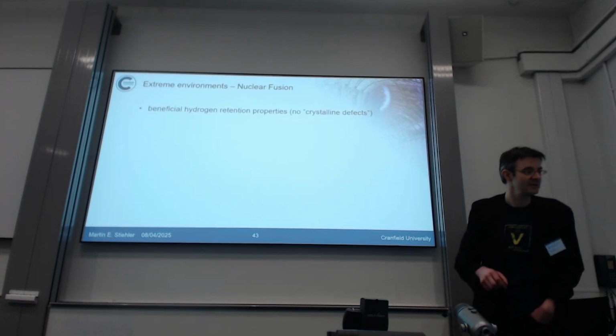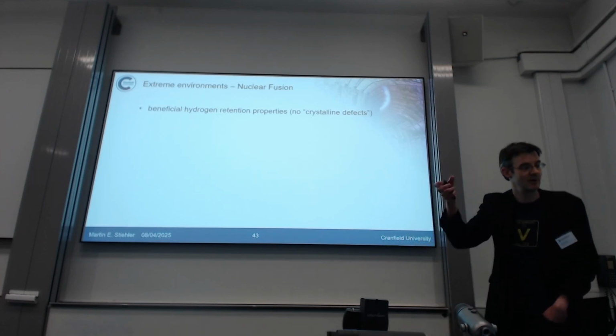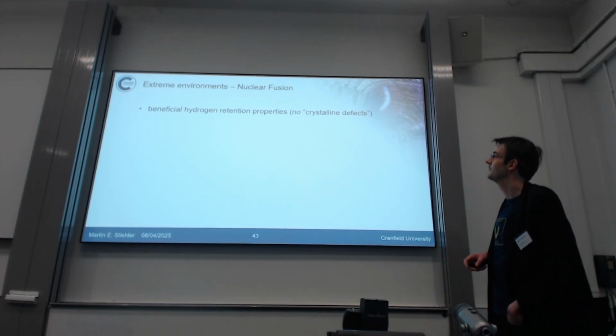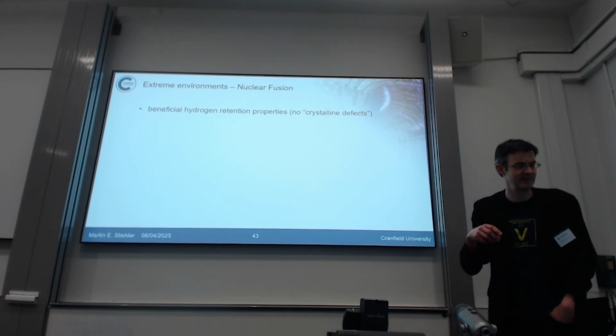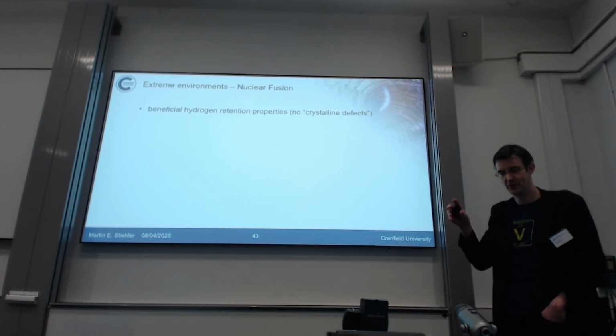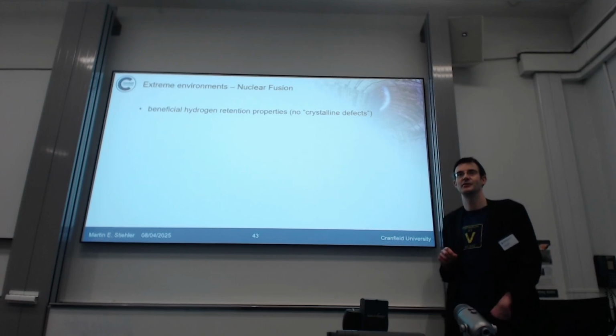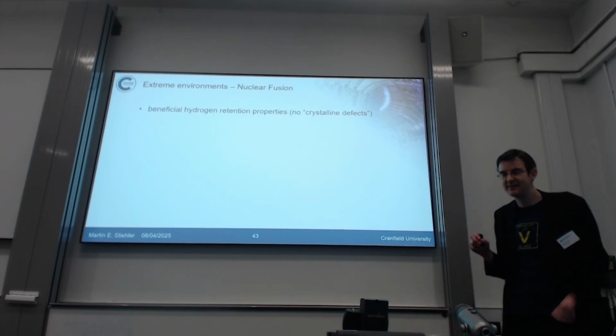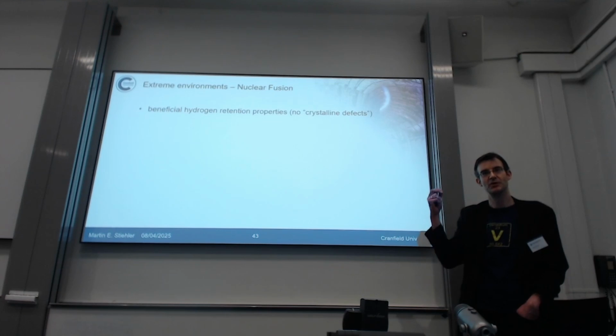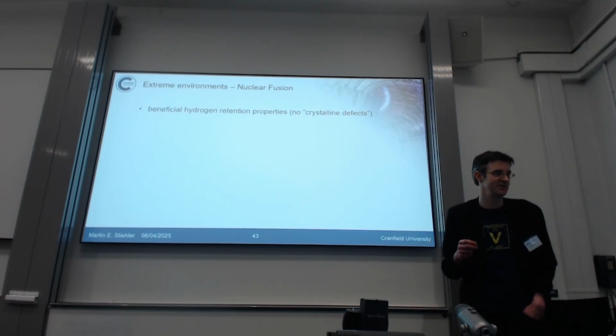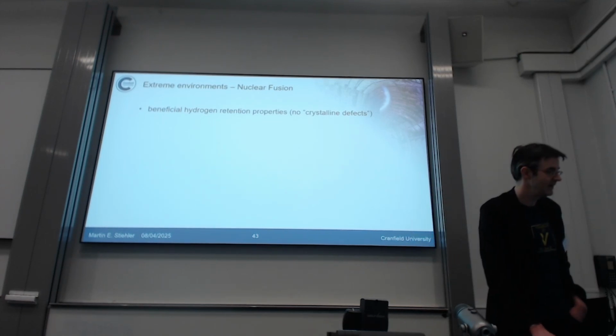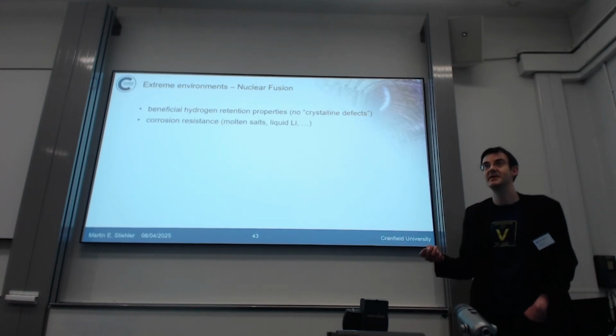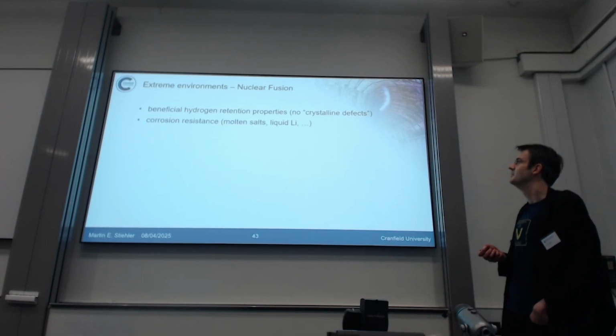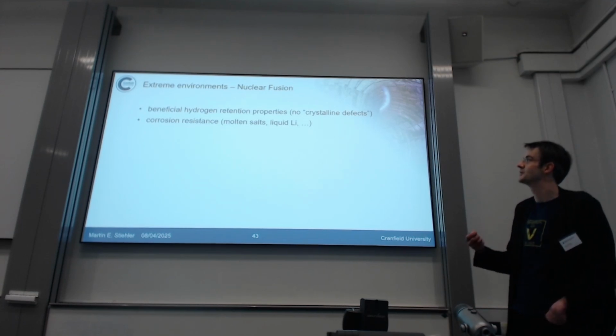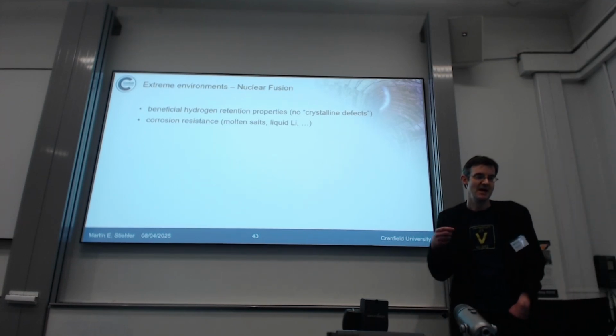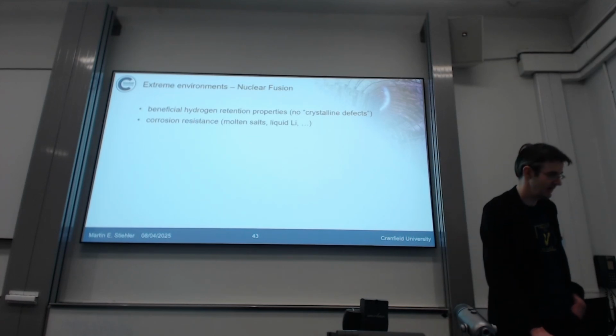There are also some other beneficial properties in terms of nuclear fusion in relation to metallic glasses. When you think of hydrogen retention, there's some problem with hydrogen or helium in the structure forming bubbles and whatnot, and this is very often related to typical crystalline defects. If you don't have those traditional crystalline defects in metallic glasses, that might be very beneficial. The corrosion resistance, as I mentioned at the beginning, is a very big part. You may know that there's a lot of discussion about using molten salts or liquid lithium in nuclear fusion, and this may be beneficial there as well.